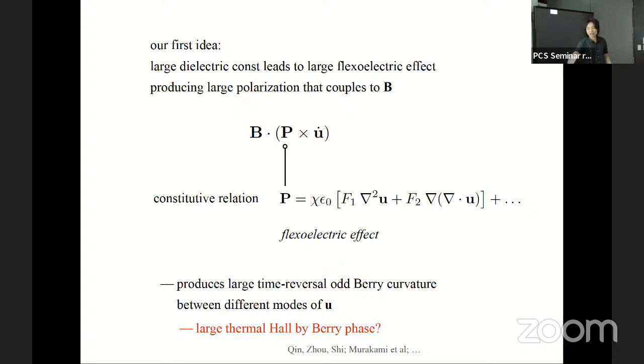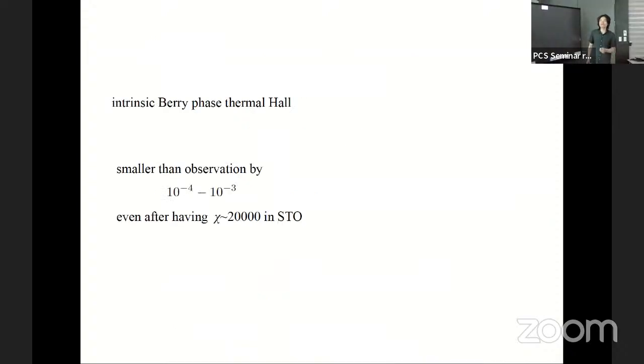It turns out this scenario has already been studied theoretically by these people, not in this particular experimental context. We can use their general theoretical result in this particular context. So what we found is that this intrinsic Berry curvature contribution, even after the enhancement of 20,000 from the dielectric constant, is still smaller than the observation by a few orders of magnitude.